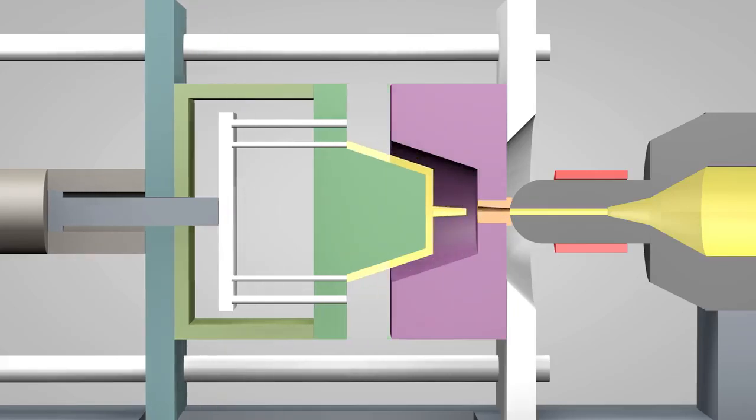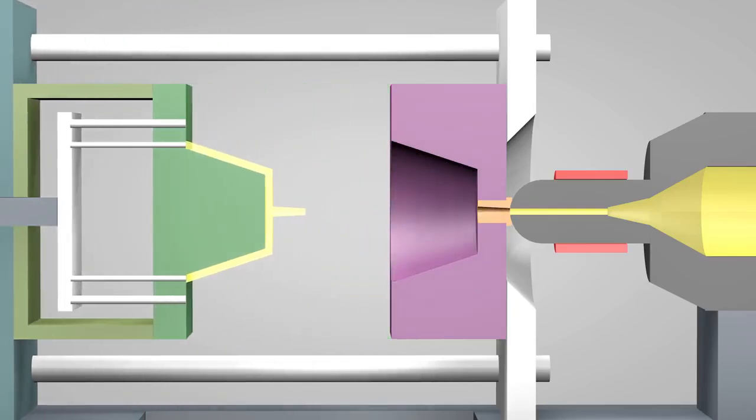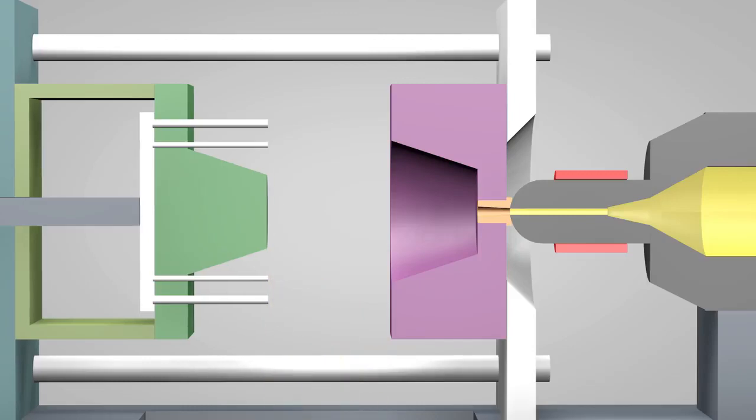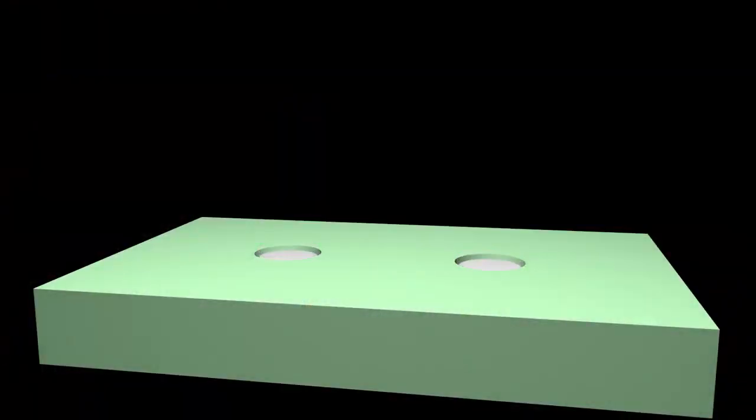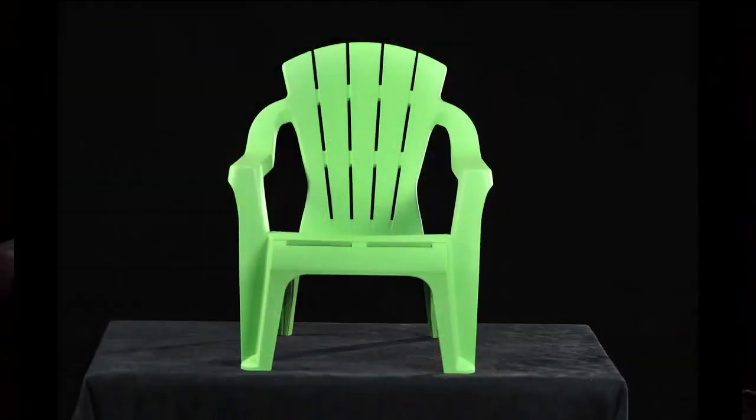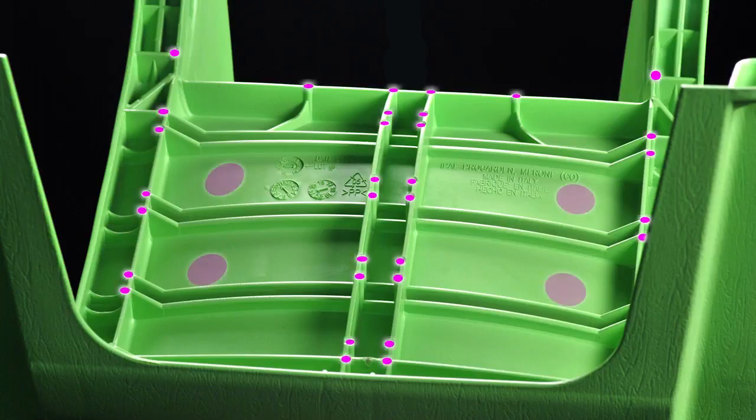Removing the part from the mold can be difficult. When the plastic cools, it shrinks and so becomes stuck tightly on the core half of the mold. Molds have built-in ejector pins that push the part off the mold. The ends of the pins sit flush with the core half of the mold, but are not perfectly aligned. Sometimes they protrude or are dented slightly. So if you look closely, you will see circular ejector pin witness marks on molded products. For example, this chair on its bottom has an array of witness marks.